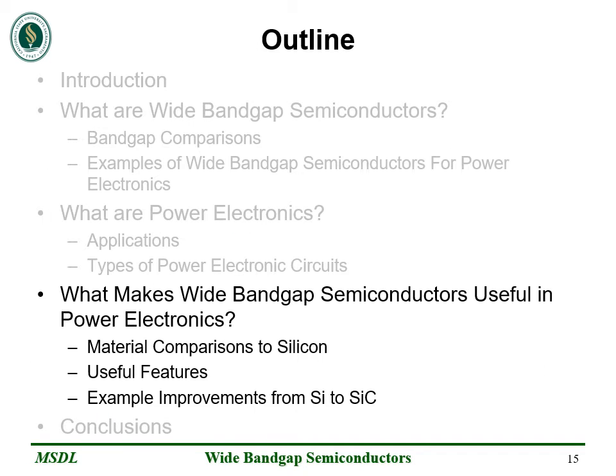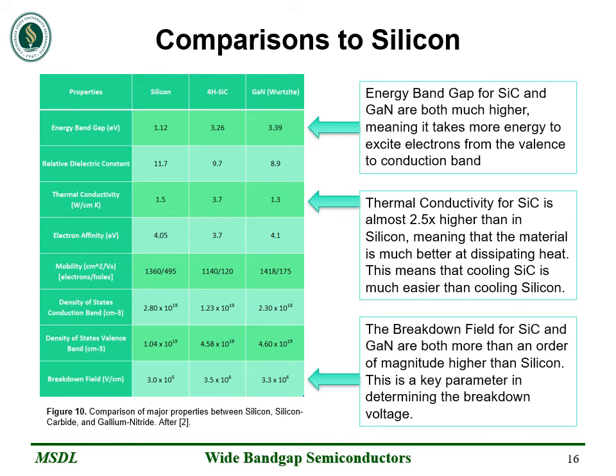It's time to see what makes wide bandgap so useful in power electronics. So let's take a second to compare silicon to some of these wide bandgap semiconductors. So the first thing that we'll notice is the band gap. In silicon, this is 1.12 electron volts at room temperature, but in silicon carbide and gallium nitride, we're roughly 3 times higher than that. And this means that it takes more energy to excite electrons from the valence band into the conduction band.